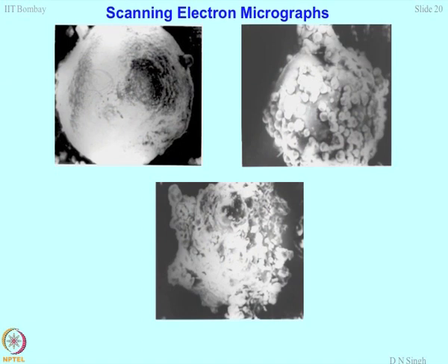A good example of this was when we were doing the Bandra-Worli Sea Link; most of the samples and analysis we have done in our laboratory. We found that if you just go by classical geomechanics and the bearing capacity you will compute, it will be highly misleading. Why? You are taking out samples from the sea which have already gone through a major mineralogical alteration in the form of zeolites. So you are just dealing with them as an SPT value, which is not correct. Truly speaking, they are zeolites, altered minerals, and they will never show you the same bearing capacity after a few years. This is where we coined this concept of mineralogical alteration of the material, and particularly how to map this information in your bearing capacity theory.